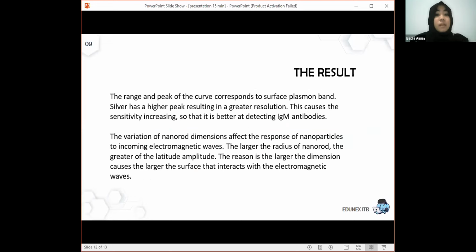And what does that mean? The range and peak of the curve correspond to the surface plasmon band. Silver has a higher peak, resulting in a greater resolution, and this causes the sensitivity to increase, so it is better at detecting IgM antibodies. Also, the variation of nanorod dimension, which is the radius of the nanorod, affects the response of the nanoparticle to incoming electromagnetic waves. The larger the radius of the nanorod, the greater the amplitude. The reason is that the larger dimension causes a larger surface that interacts with electromagnetic waves.